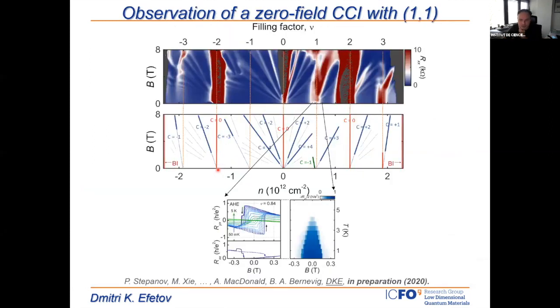Basically, let me move on. So these states can also appear, as I mentioned, at zero field. For example, in this particular device, which is very comparable to all other devices I showed, it shows superconducting phases, it shows correlated insulators, but it also shows, in zero field, centered around filling factor 1, a very strong hysteresis loop if we measure Rxy, depending on the magnetic field direction. So there's clearly some magnetic state which is formed around filling factor 1. And this magnetic state is identified by the hysteresis loop, and it's almost quantized as well. If you look at the Rxy value which we obtained here, it really has an almost quantized value of a Chern number 1.